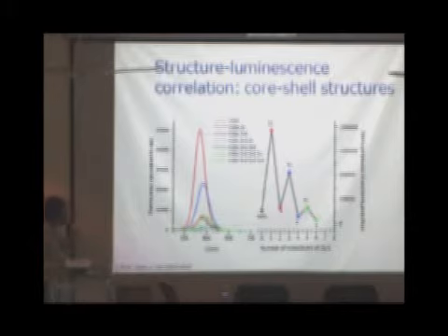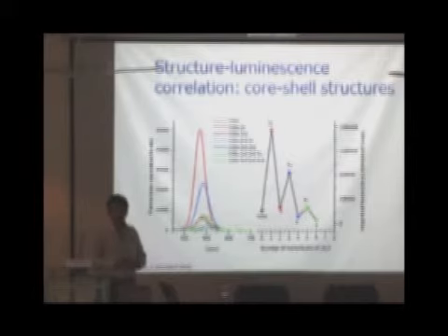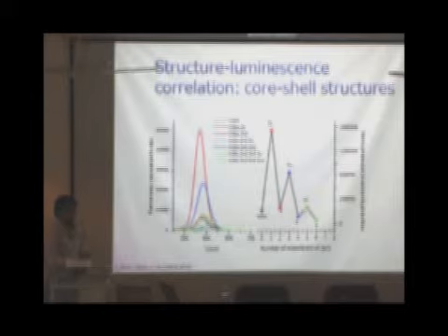The very interesting thing was that it really depends on the kind of surface atoms that you have. Surface plays such an important role. So if I coat one monolayer of zinc, the fluorescence intensity shoots up. But then if I coat a second monolayer of sulfur on top, intensity comes down. So zinc is very crucial.